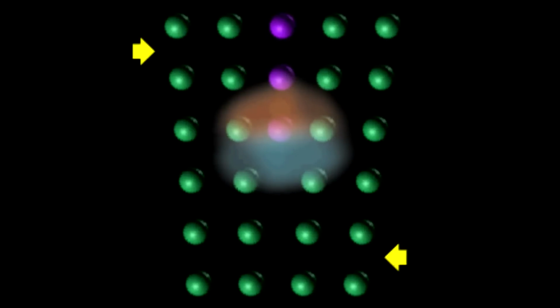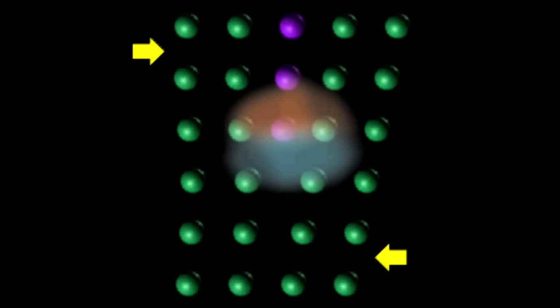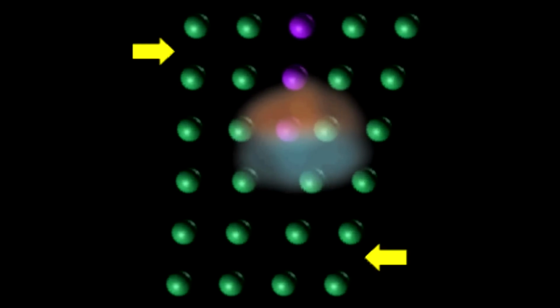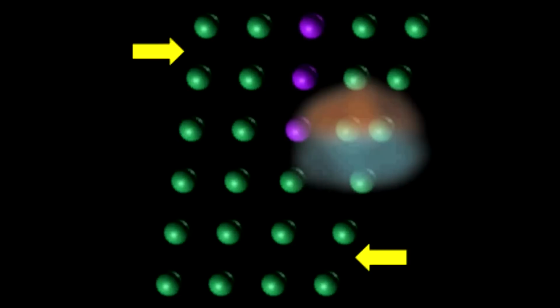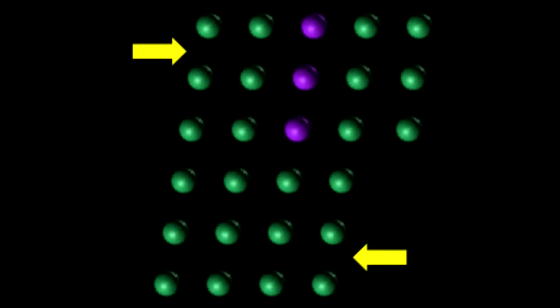When a shear stress is applied, the initial extra half plane of atoms is forced to the right. If the applied shear stress is of sufficient magnitude, the interatomic bonds of the plane next to the extra half plane are broken. This process is repeated for other atomic planes until the extra half plane emerges from the right surface of the crystal, forming an edge that's one atomic distance wide. Macroscopic permanent or plastic deformation corresponds to the formation of ledges resulting from the motion of large numbers of dislocations.